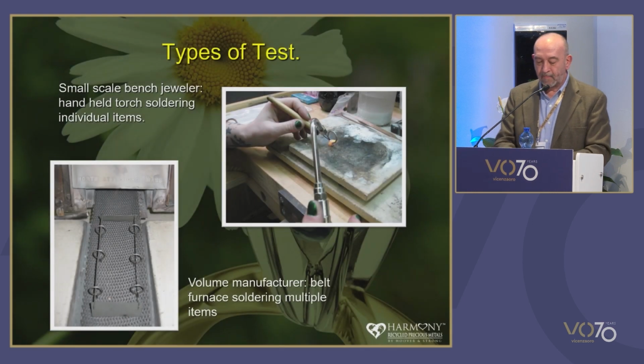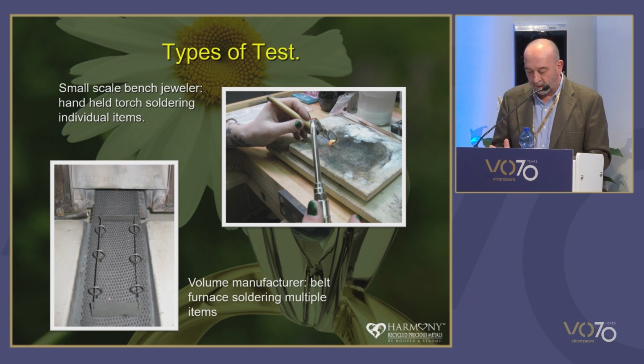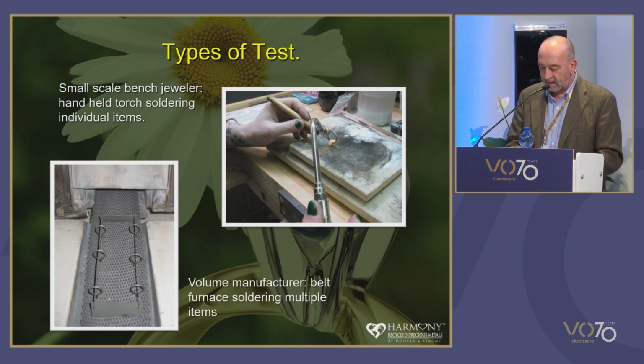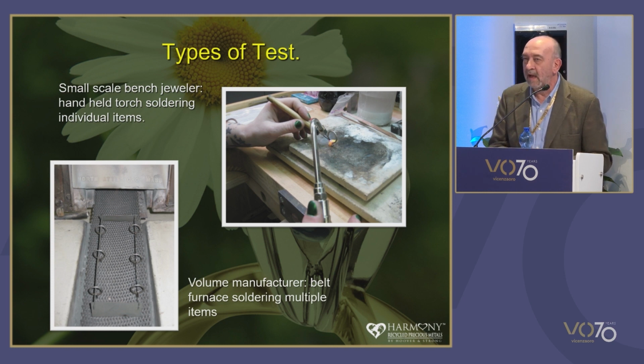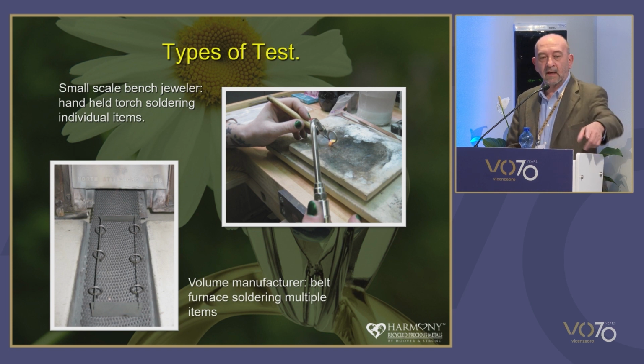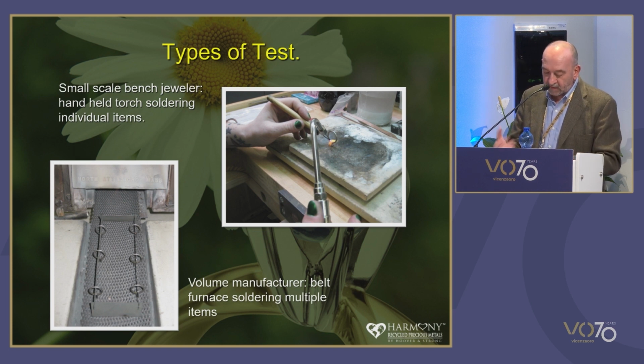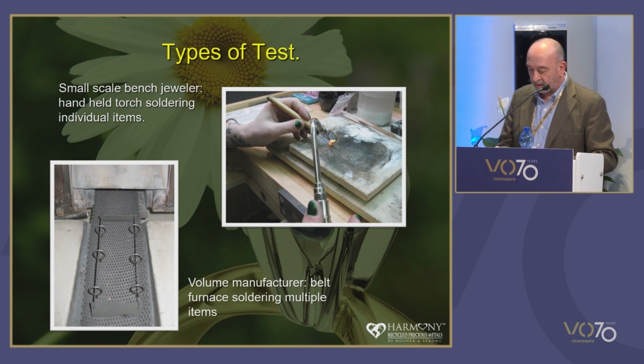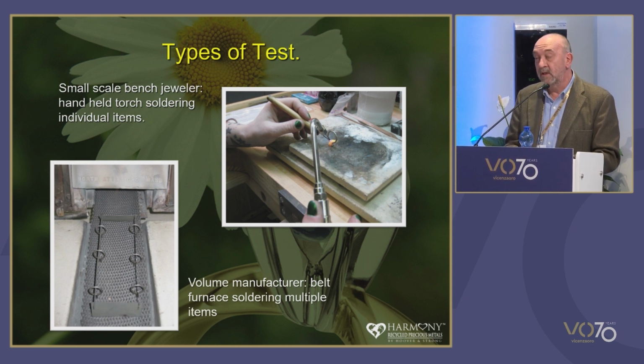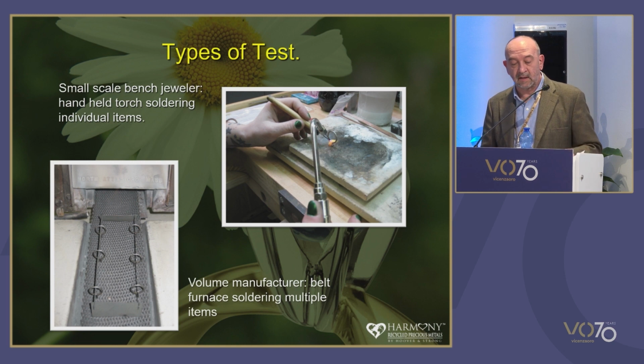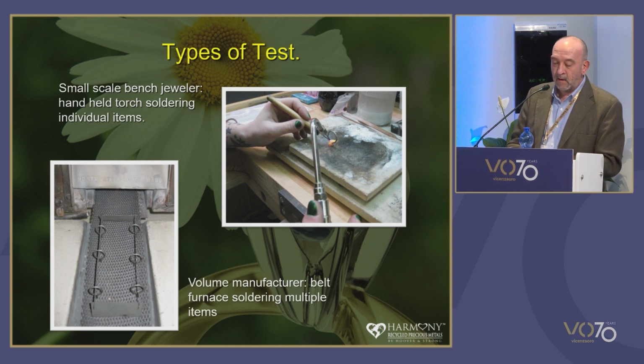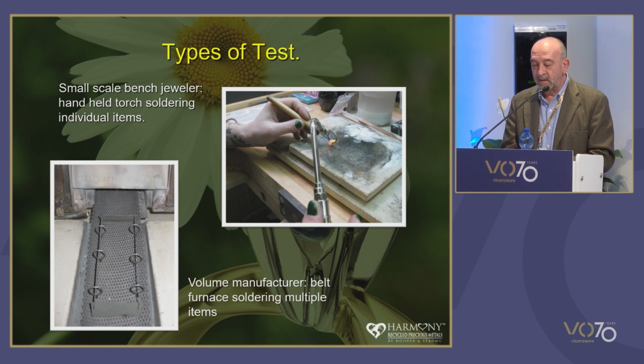On the small scale, a bench jeweller usually works on individual items, one at a time, using a handheld torch, so an open flame, as the heat source. A volume manufacturer is going to assemble multiple items at the same time using jigs, usually in an atmosphere-controlled belt furnace. And you can see a little example of those on the picture there. So for this study, each test is going to be processed in these two ways. For torch soldering, boric acid was used as a flux to protect the workpiece, and in the belt furnace, cracked ammonia was used as the protective atmosphere.